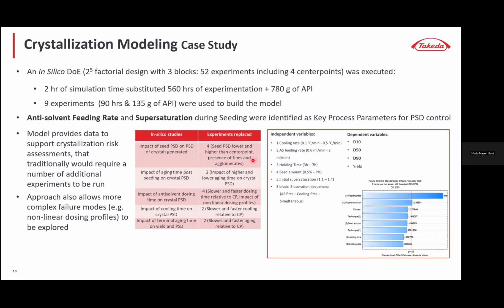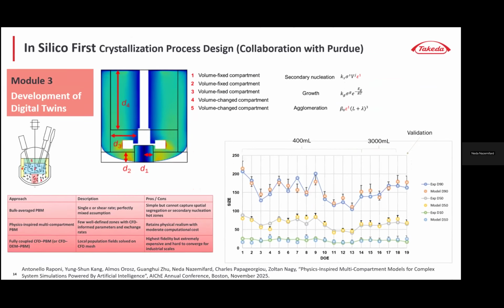In addition, the model predictions provided data to support the risk assessment for the crystallization. Traditionally, to thoroughly assess the risk, like what happens if we deviate from the ideal feeding rate, you have to run a bunch of extra experiments, but here we can simulate these scenarios. It also let us explore more complex what-if scenarios, for example, if we have a nonlinear dosing profile, how that might impact the crystallization, without doing it experimentally. In summary, the PBM model combined with this in silico DOE let us do in days what might have taken weeks otherwise, and it also pinpointed the key factors for a robust process.